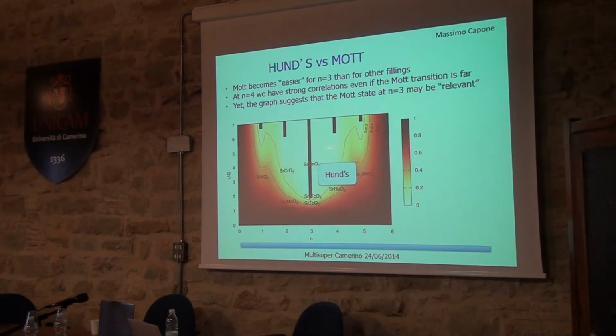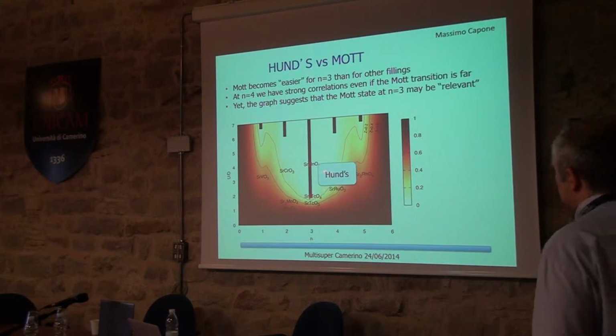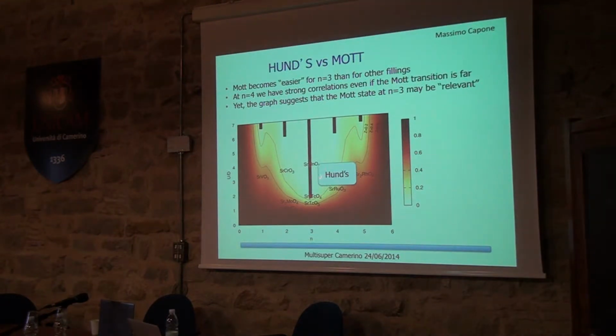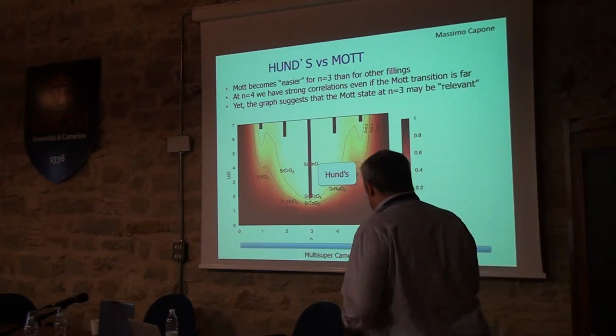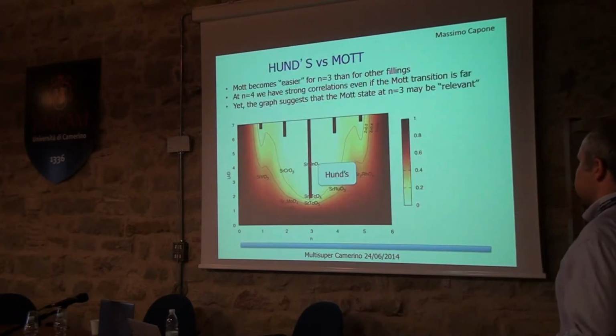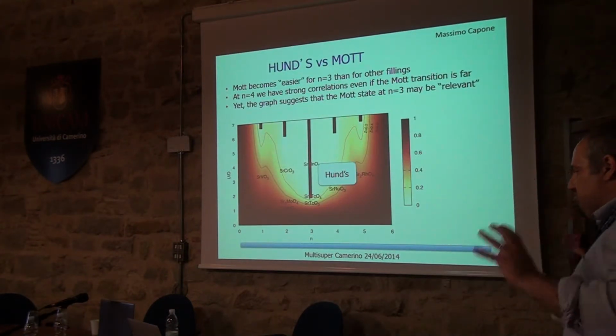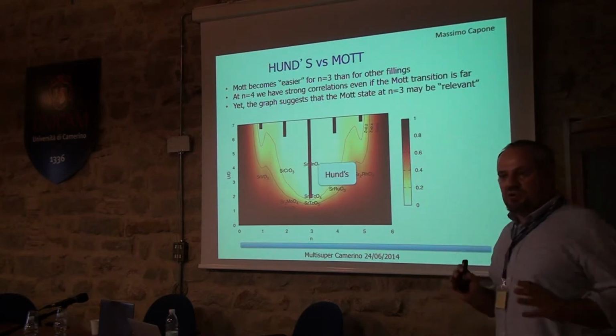So we are sitting here essentially. What the graph suggests is that this Mott state here might still be relevant to understand what happens here. So you should not think of the Mott state as being very far at the same number of electrons you have. But you really should think that you're sitting at some doping from this other, much stronger Mott state. So this is what we learned before attacking the iron-based superconductors in this way.